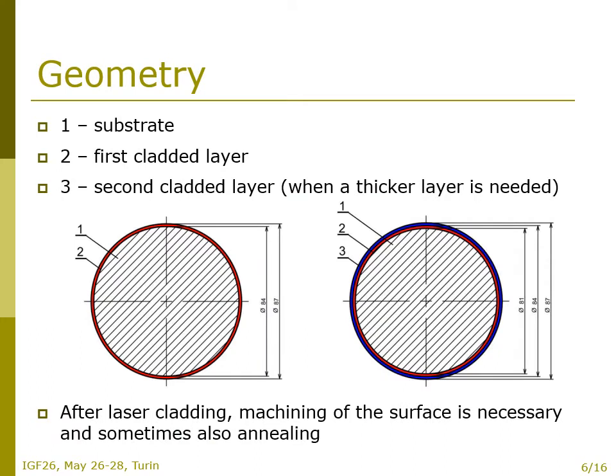With regard to the real structures, the following geometry was chosen for numerical simulations. The outer radius of the component is between 80 and 90 millimeters, where the substrate represents the massive part of the component and a thin layer or two are cladded on its surface. After laser cladding, machining of the surface is necessary, and sometimes also annealing.